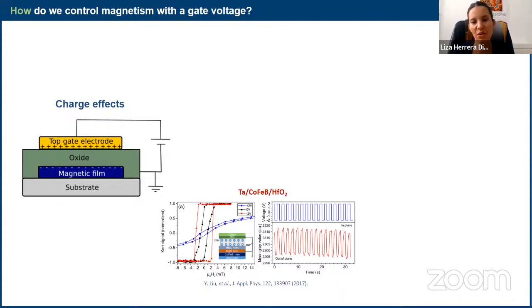So here, hafnium oxide is used just as an oxide and not as an ionic conductor. And here we could see the black and the blue and the red curves. So here you go from an in-plane magnetization to out-of-plane magnetization, switching from +2 to -2 volts. And what we did with this was to have fun with this device and then apply a constant magnetic field out of plane and then switch the voltage up and down between +2 and -2. And then with the Kerr microscope, we could see how the magnetization was following the direction of the easy axis. So then in principle, you can switch the magnetization just by using a gate voltage